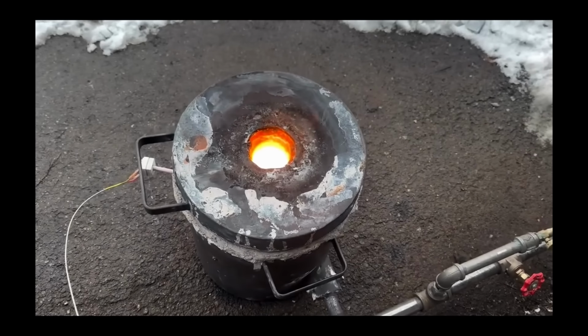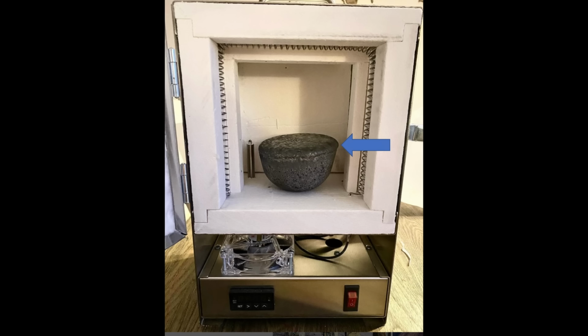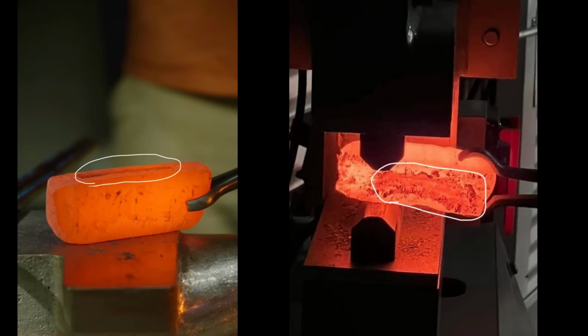These are not big commercial steel making facilities, and so there can be more impurities because of that. Also, Spencer told me that when he normally forges these ingots, he forges all of the junk material that ends up on the top of the ingot to one side and then grinds it away. In this case, he decided to keep it in the center of the billet to grind it off of the surface. And you can see some pictures here.